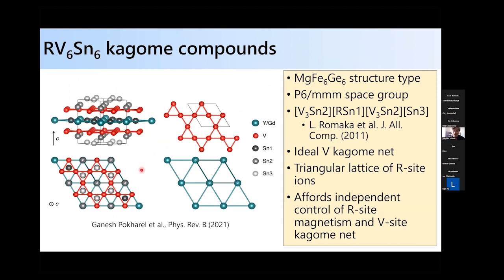So first off, just a quick overview of the structure. You are all familiar with this. Basically, these are ideal kagome nets, and in this case, vanadium ions, which are non-magnetic in these materials. This forms a bilayer structure, and in between these bilayers, you form a triangular lattice of rare earth ions. So the idea is that you can try to realize or manipulate filling control in the non-magnetic kagome net, and then interface that with a variety of different magnetic states that are realized in the triangular lattice network of rare earth ions. So in an ideal scenario, you perhaps have independent control of the two.